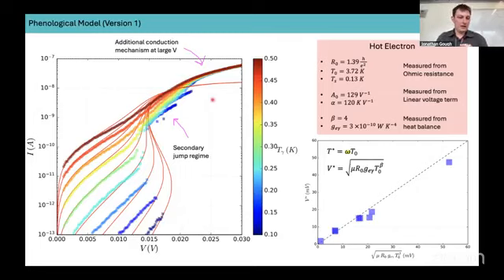Two-terminal measurements are not as ideal as a four-terminal measurement because you get things like contact resistance and series resistance associated with the leads and the wiring. However, these samples are gigaohms, so a kiloohm from the wiring is not a big contribution to your resistance. So two-terminal measurements work very well. You can either source current or source voltage. If you're sourcing current, you essentially have to charge up the capacitive part of your circuit, so it has a very long settling time. So instead you apply a voltage and measure current.